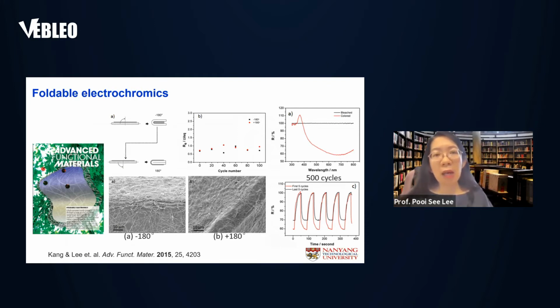In this case, we prepare a transparent paper using nanocellulose that can be casted onto a wide area. Because of the very fine structure of the cellulose that has been extracted from nature, we can see that upon casting them, in this case, a vacuum filtration method has been used. It leads to a transparent paper that is very robust, which can be folded to 180